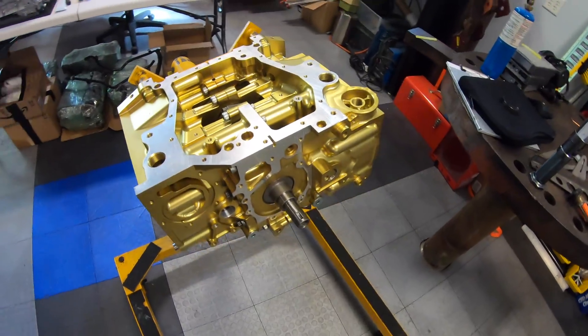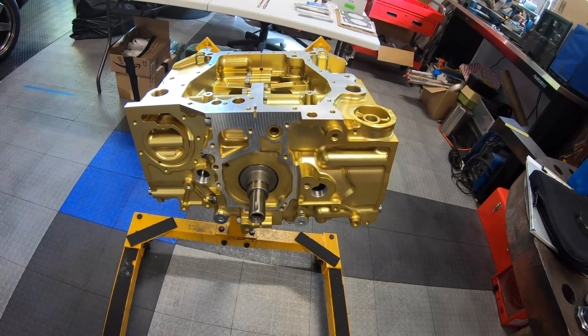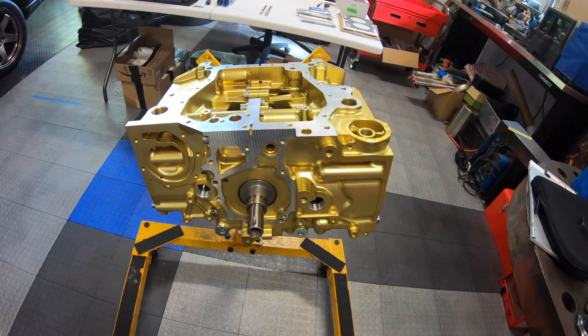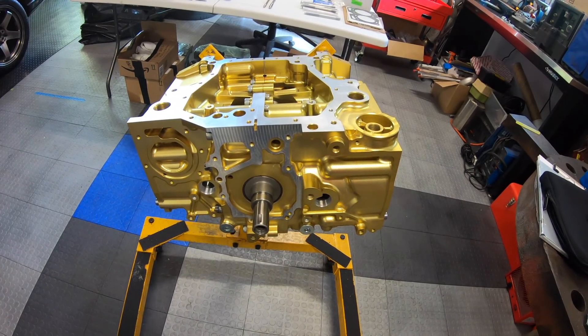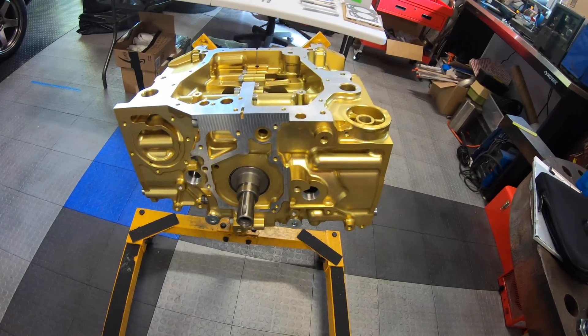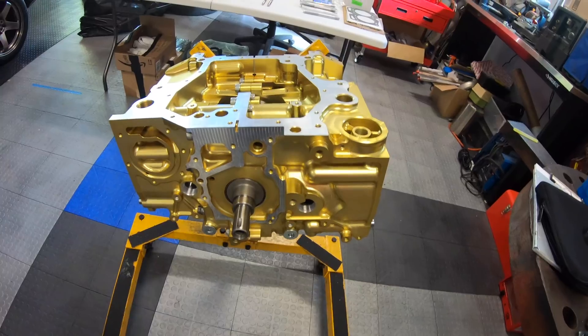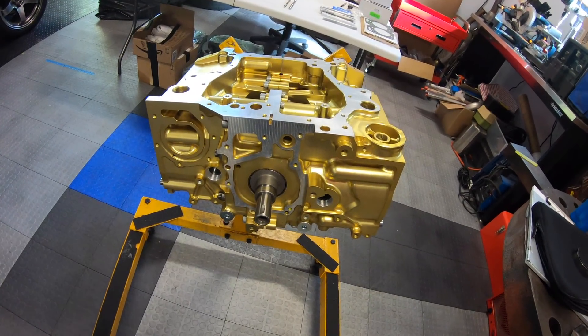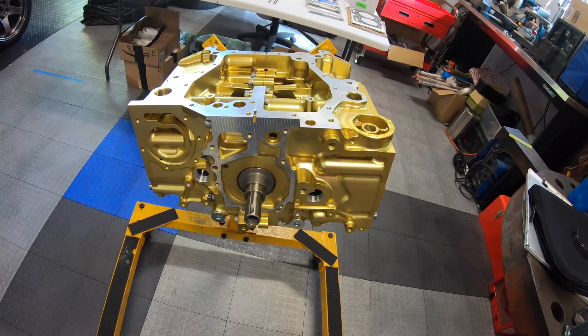On the front, the oil pump and water pump connection interfaces are the same, so all the factory timing belts, tensioners, and those things bolt up like stock. This one has a Manley crank in it, which is a 4340 billet crank — heat-treated, nitrided, and balanced. The rods are the IAG 2mm longer tri-beam rods, and the pistons are IAG 2618 material with the beefier 0.210-inch wrist pins.